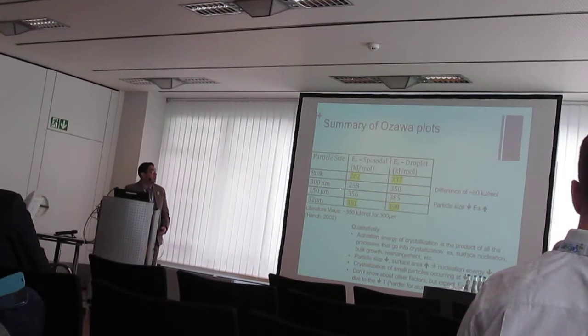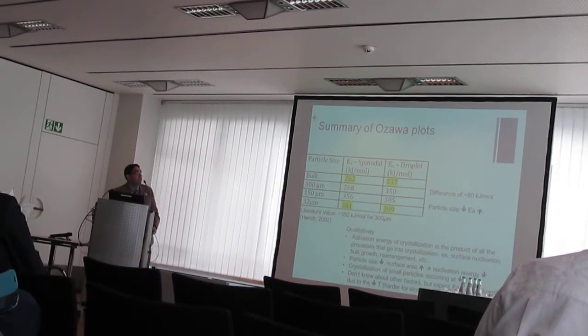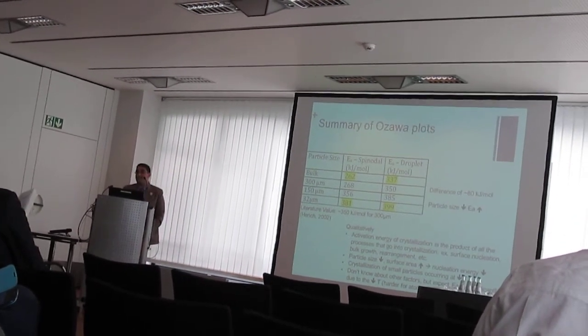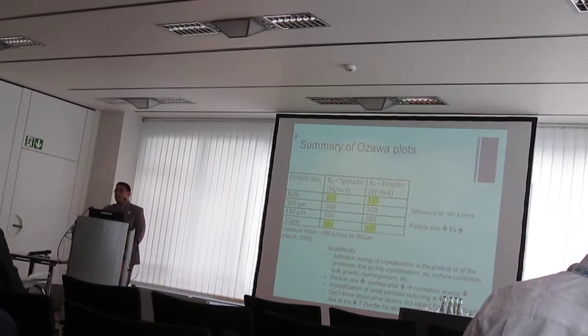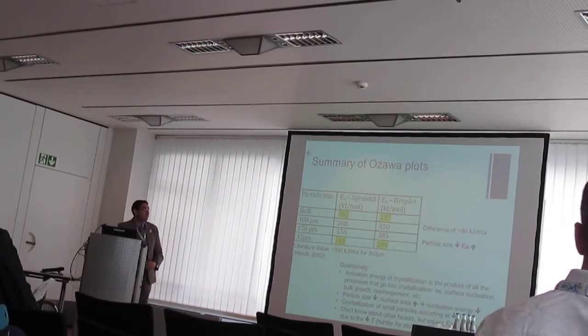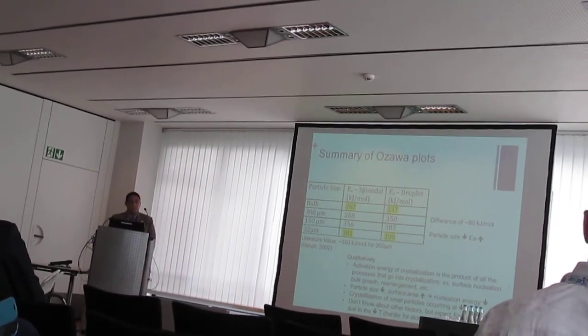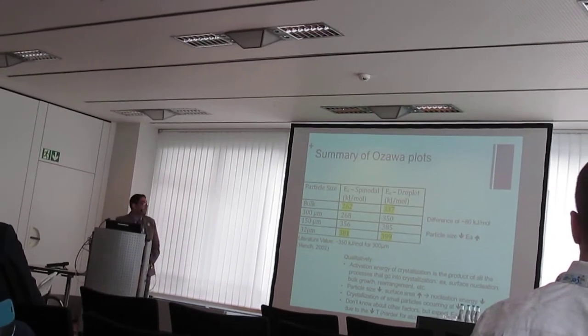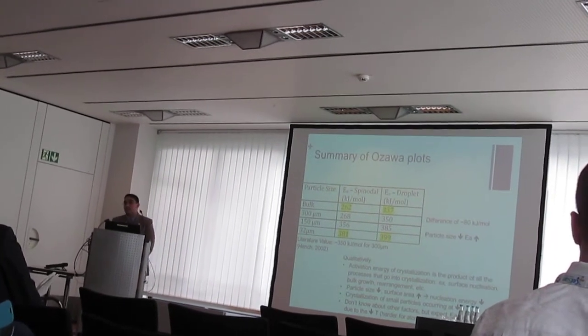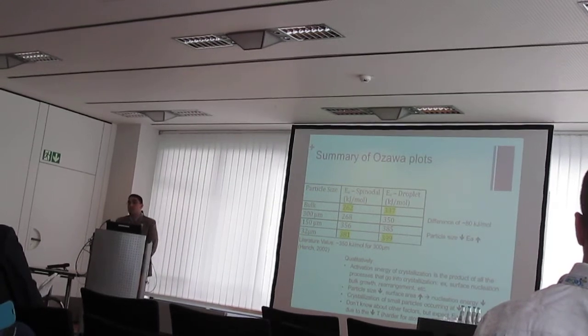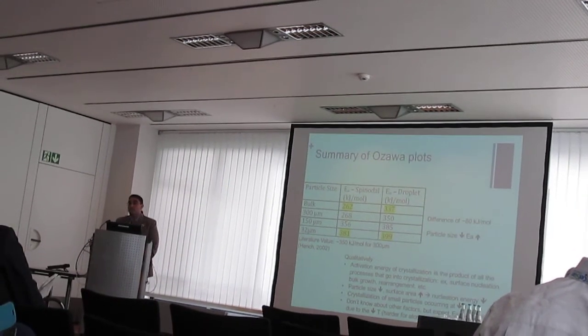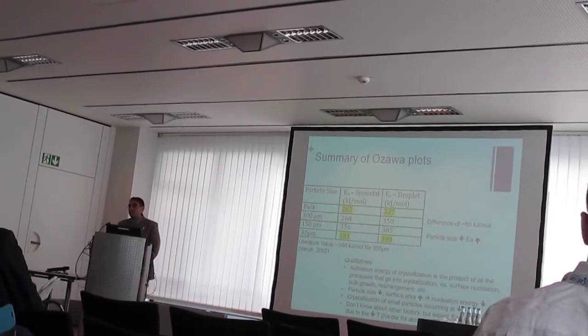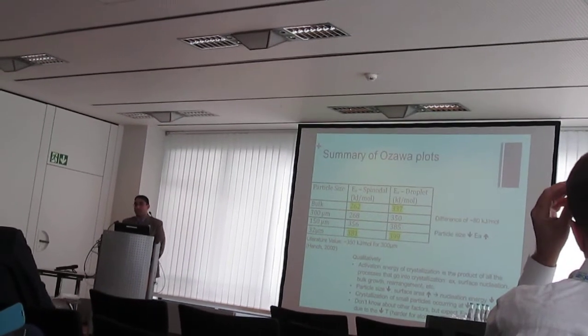The other thing that I want to point out is that, once again, as the particle size decreases, the activation energy of crystallization increases for both bioglass. As I said, this was counter to what we first hypothesized, because the nucleation energy should decrease as the particle size decreases.